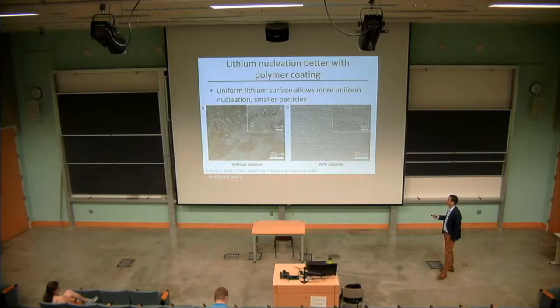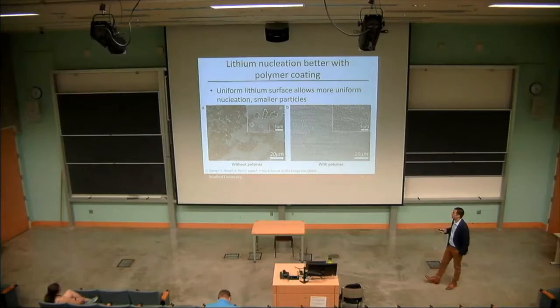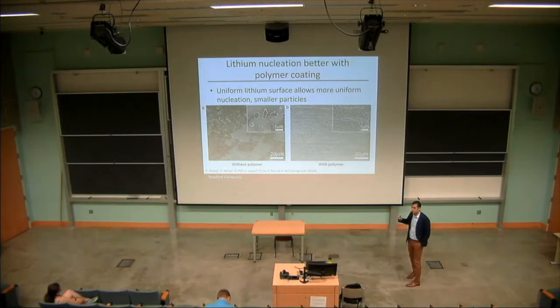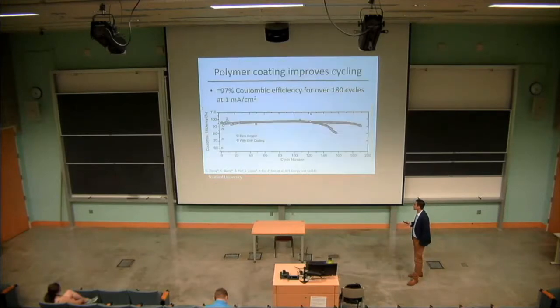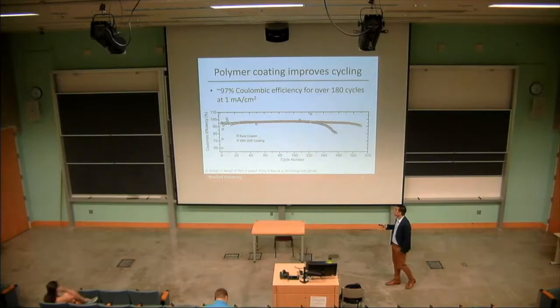Whereas when we have the polymer coating, we see highly uniform and much smaller lithium nuclei in the presence of the polymer coating. And so we think that this process, control over that nucleation and growth, is what's key to controlling the eventual structure of your lithium metal.